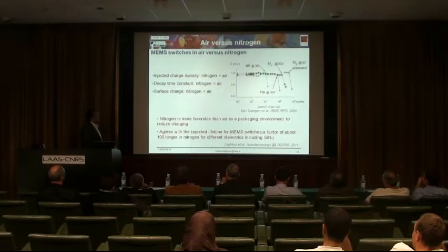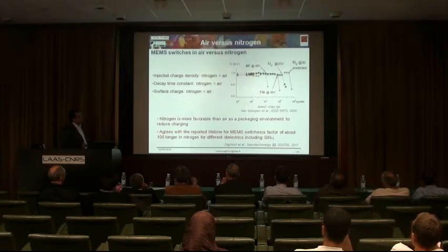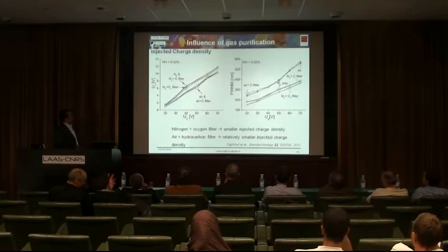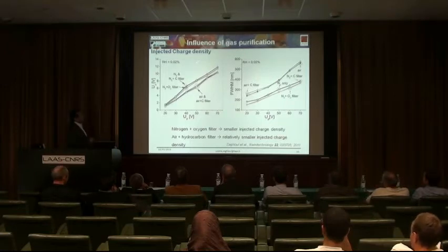This actually agrees with the published data from IMEC, where they have shown that the lifetime in the case of air is shorter by a factor of 100 than in the case of nitrogen. Our technique helps to understand what happens with different environments. The last thing we have done, and I should go very fast for this, is a different gas purification where we use different filters.